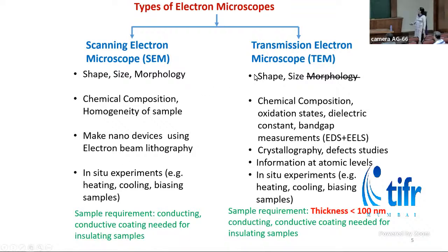Transmission electron microscope can also show you shapes and size of the sample. But here, since the image is formed by the electron beam which is passing through the sample, it cannot show you surface morphology. So SEM gives you 3D kind of image, which gives you a surface morphology, which TEM cannot give. If we have EDS attached to TEM, we can get the chemical composition of the sample. If we have EELS, electron energy loss spectroscopy, attached to the TEM, we can get information about oxidation states, dielectric constant, band gap from the sample.